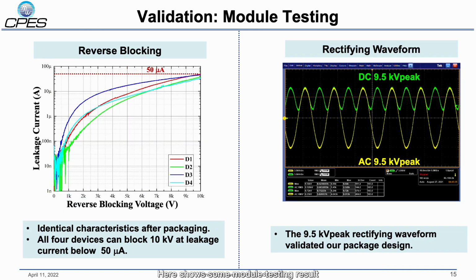Here shows some module testing results to validate our package design. Here shows the reverse blocking test. All the diodes were characterized after packaging. They showed identical characteristics after packaging. All four devices can block 10 kV at leakage current below 50 microamps. Here shows the rectifying waveform. The 9.5 kV peak rectified waveform validates our package design.